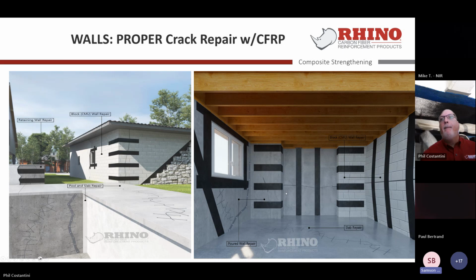Okay, but there's an application, let's say with a T-beam, where the whole vertical face of the T-beam has a shear crack, and it's only like 2 feet, something like that. Would that crack lock work in that application? For a 2 foot, absolutely. I mean, if it's coming off a corner, is it a situation where there's no displacement, where the wall hasn't moved or shifted? It's a crack, let's say a T-beam with a typical classic shear crack, Phil. Yep. You could just put these crack locks in there every, whatever, 4 inches on center, whatever the appropriate number would be. Yeah. So 100%. Absolutely 100%. I've got no issue with that.